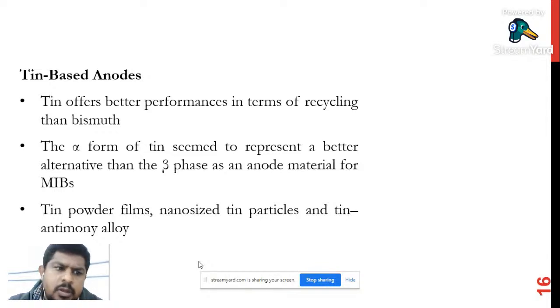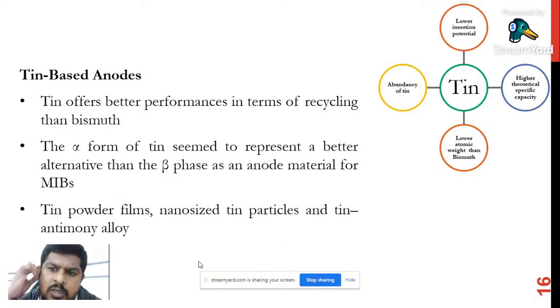So here one is atomic weight, and the availability of tin is also comparatively more than bismuth. Then it has higher energy density values. Now, based on the researchers, they have found the tin with antimony alloy. This is what the researchers have been working on, and they have found it.